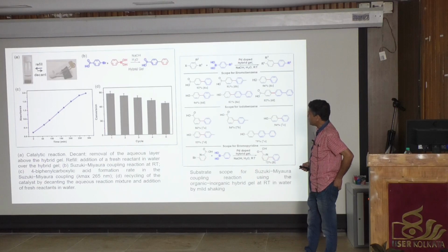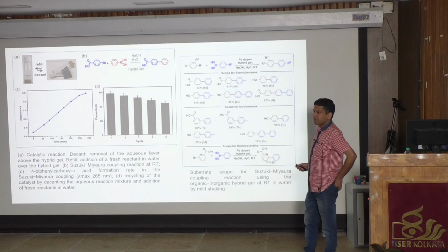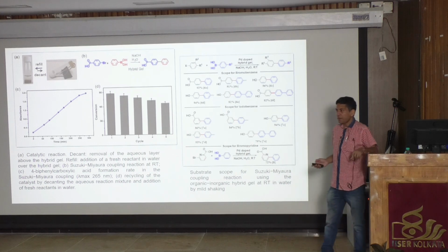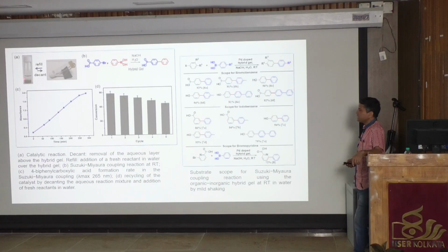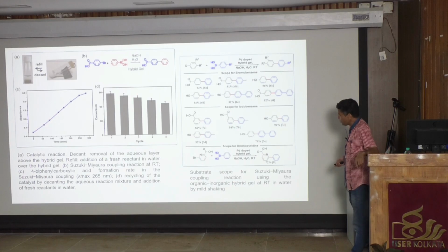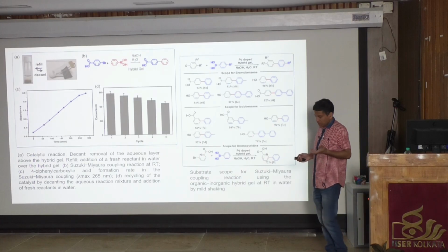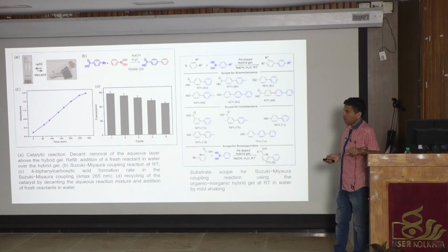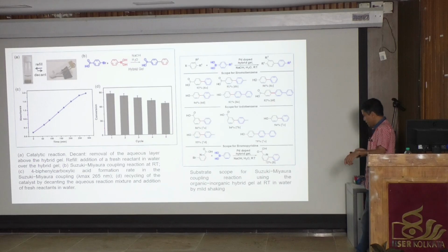Again we can top up with the reagent and do the reaction. We have done this reaction up to 5 cycles with almost 70% yield, which is not bad, because every time we decant, there is a possibility of some leaching of the palladium nanoparticles from the gel matrix. And this is the substrate scope. We can do this with the brominated compound, with iodobenzene, or with the pyridine unit as well. So we have a lot of substrate scope for this kind of reaction. The same catalyst we can use multiple times. We can do the Suzuki coupling reaction at room temperature in mild condition without stirring, it's just sitting. And we can easily isolate the product simply by acidification and then filtration.